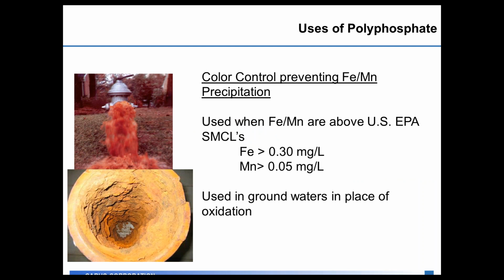So when we talk about color control and the use of polyphosphates for sequestration, typically what we would say is when you're using it for iron and manganese sequestration, you're above the US EPA secondary maximum contaminant levels. Those secondary maximum contaminant levels are aesthetics. They're not health effects. So water that contains iron above 0.3 milligrams per liter and manganese above 0.05 will cause staining of fixtures and laundry in the consumer's home. If you're above those levels in the water that goes out the door to the consumer, you would use a polyphosphate to sequester them so they don't precipitate out and cause those color issues in the distribution system.